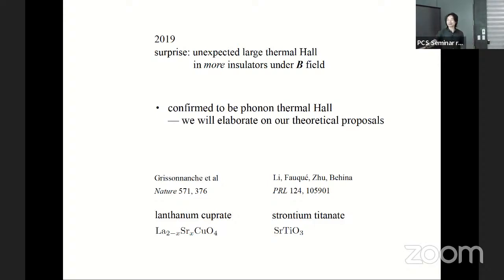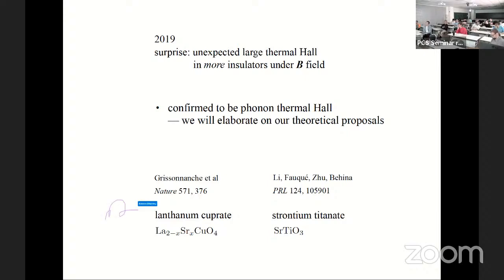And then by this further experiment, as well as our theoretical phenomenological analysis, we confirmed that this is to be attributed to the phonons. So these are phonon thermal Hall effects. We will elaborate on our theoretical proposals, and we'll explain why people didn't think about phonons at the beginning. How can you confirm that the phonon contributes? Yeah, I'll explain later. That's the whole point. Because in the past, people thought phonons should not be relevant at all.